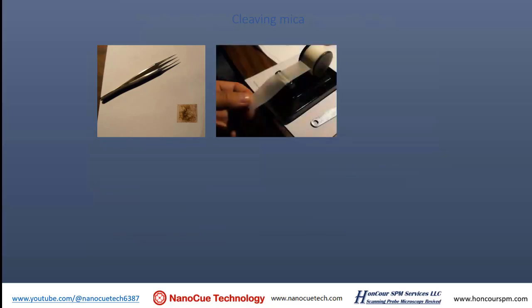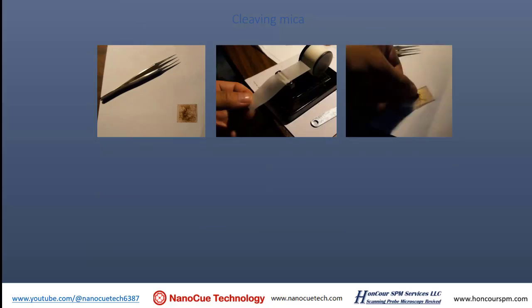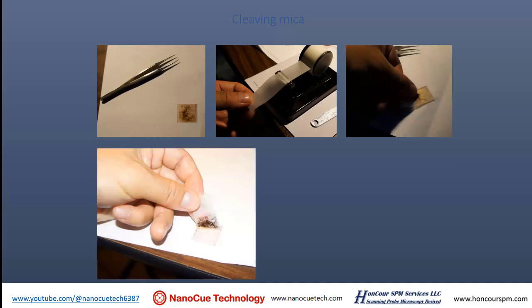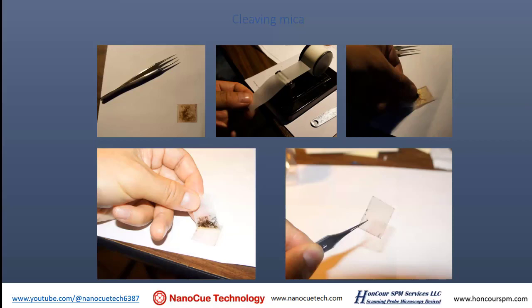You take a mica and you pull out a tape, Scotch tape, and then rub the tape on the surface of that mica, and you peel your tape off and expose the clean surface. You don't need to clean the overall sample. You just have to clean the middle because that's all you need for an AFM image. And then you have clean mica, and it's guaranteed.